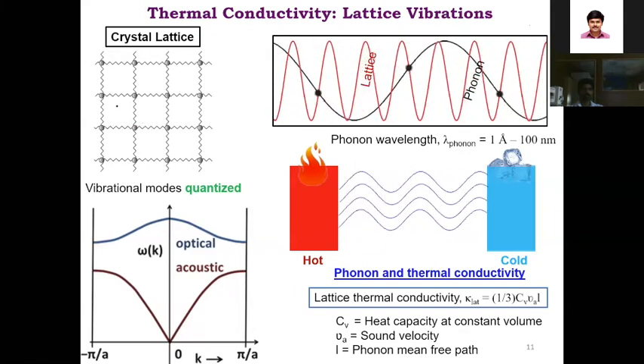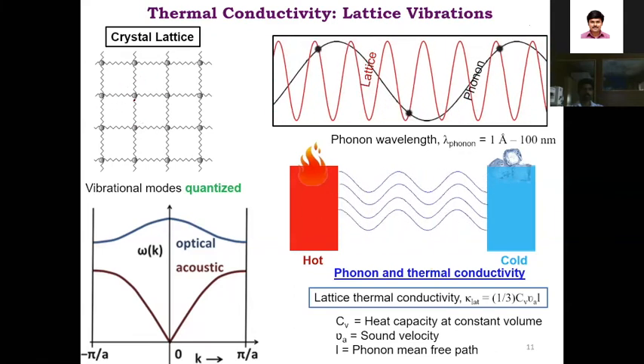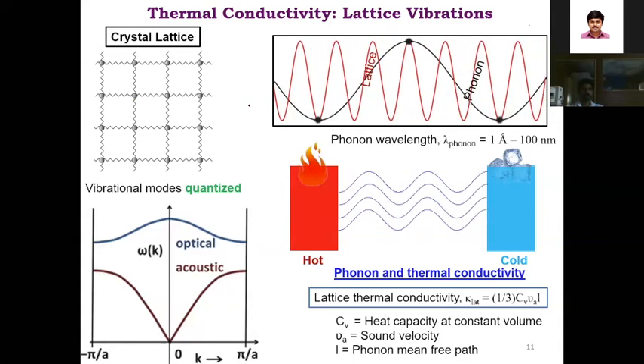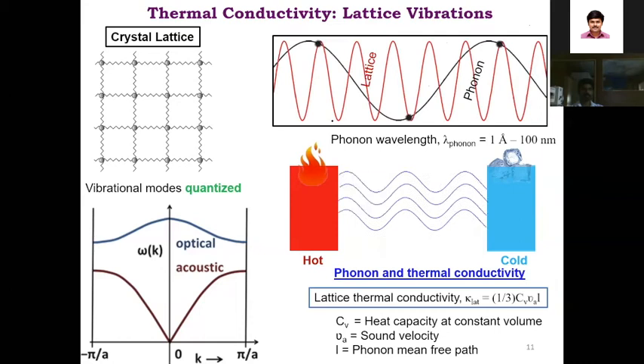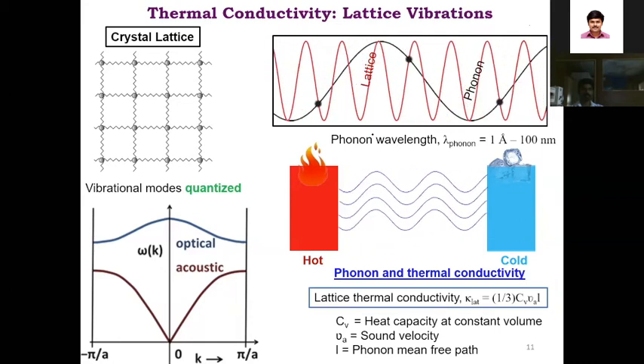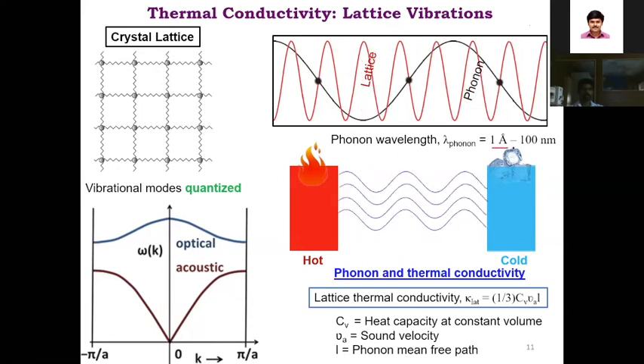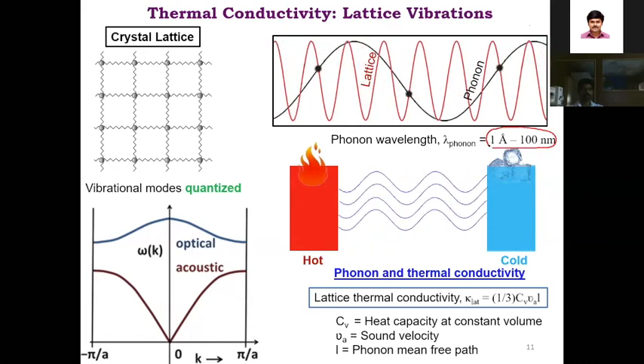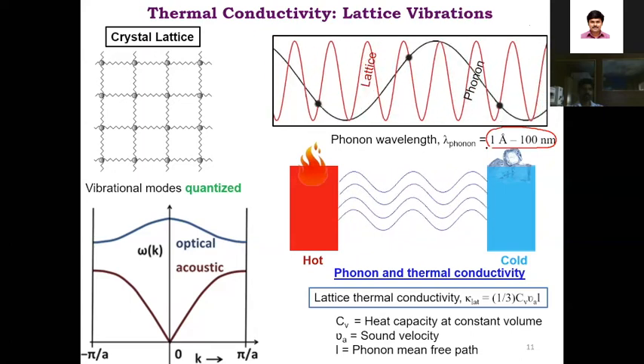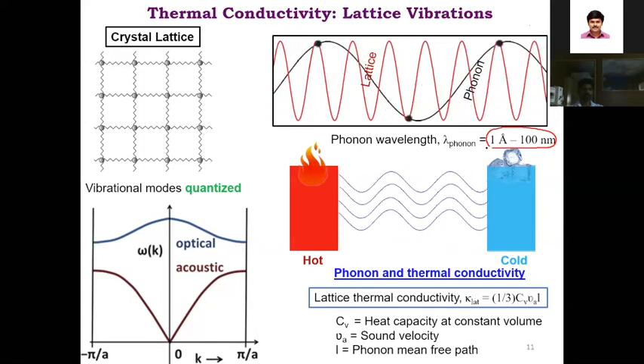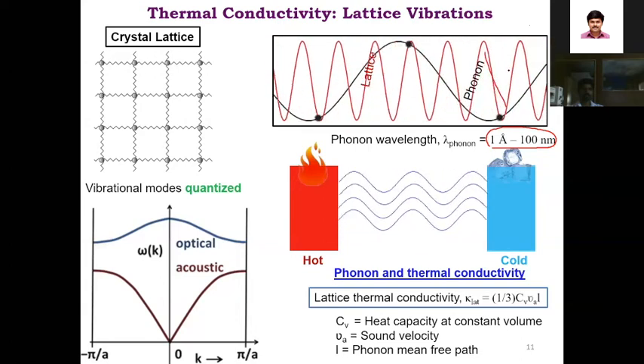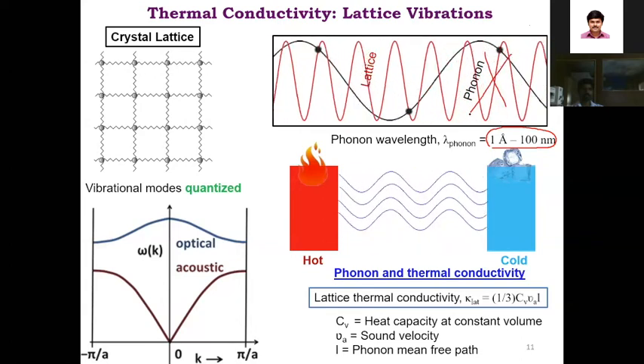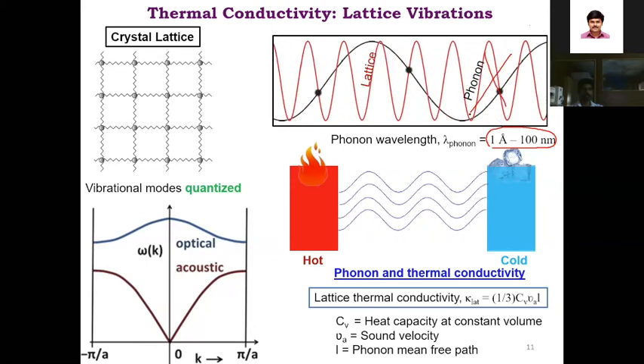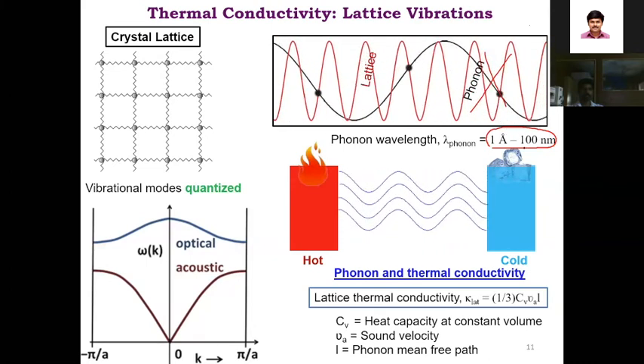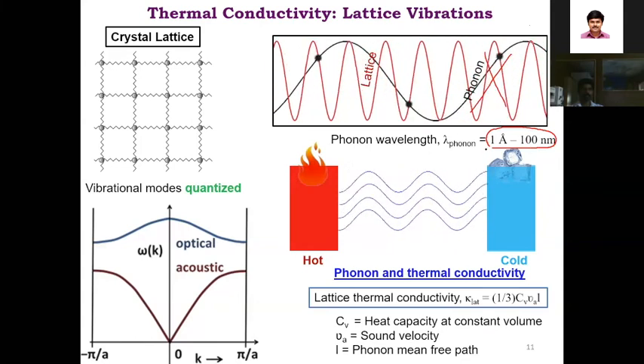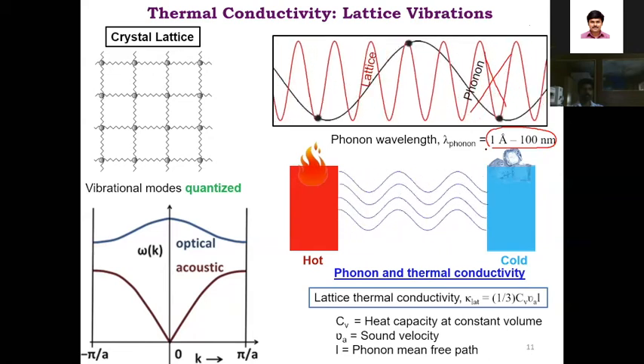So now this is the crystal lattice, and crystal lattices are formed by atoms, and this lattice vibration gives rise to a quantized vibration, which is called phonon. And the phonon wavelength, which generally carries heat in these tellurides and selenides, is in the range of 1 angstrom to 100 nanometer. So if we want to decrease the thermal conductivity, one way to do it is to block this phonon movement, so that phonons will not pass from one end of a solid to another end. To do that, we have to have some object which has a size similar to the phonon wavelength. I'll come to how we can do it in a minute.